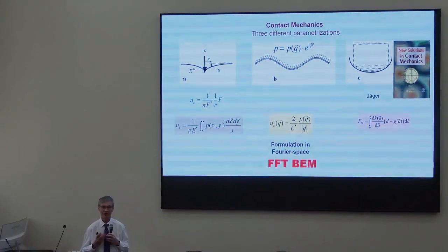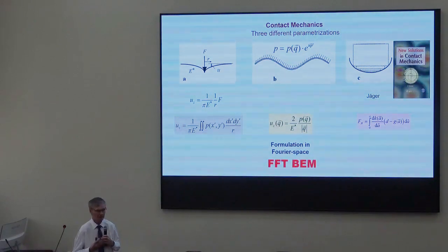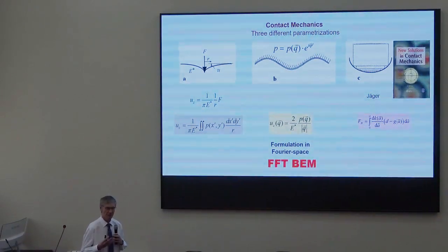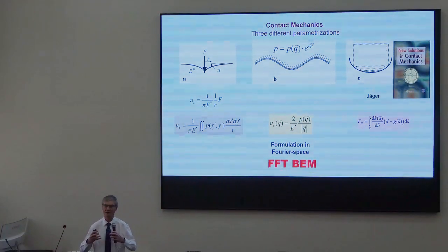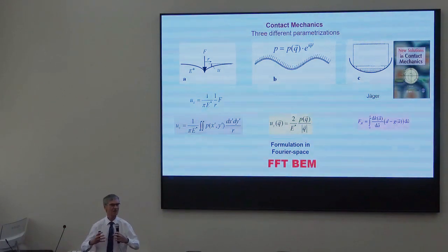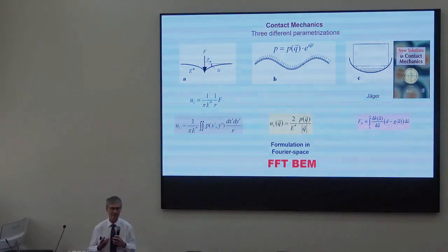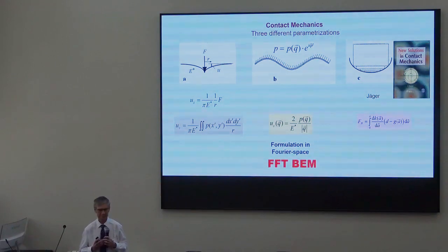If we consider axisymmetric indenters, then the indentation of such an indenter can be represented as incremental indentations by flat-ended cylinders of increasing radius. And the basic functions are, in this case, the solutions for flat-ended cylinders.